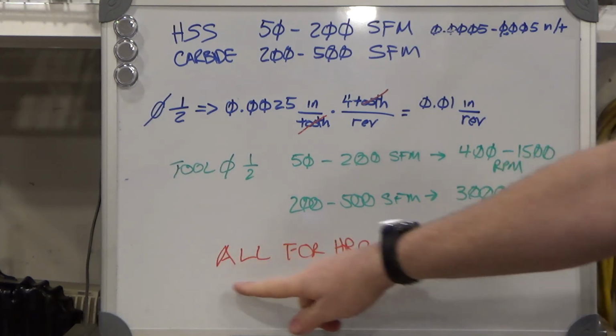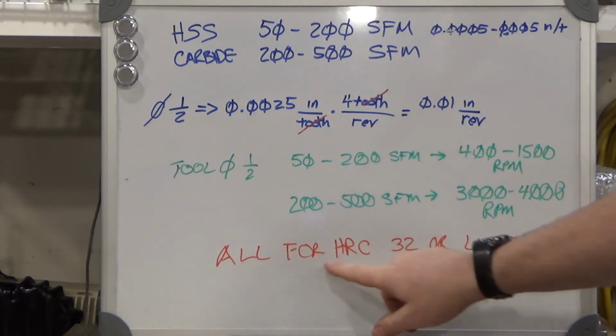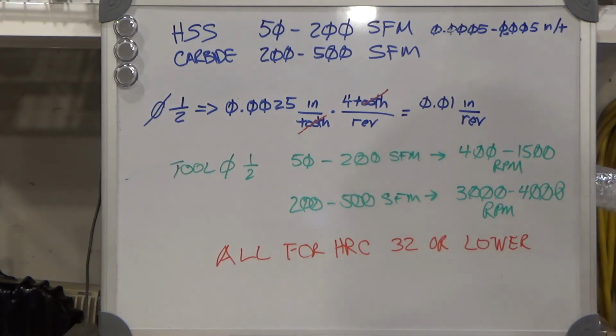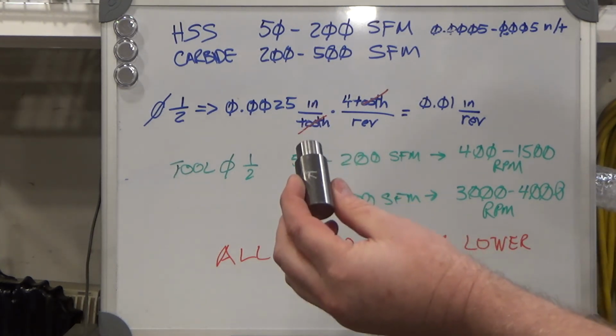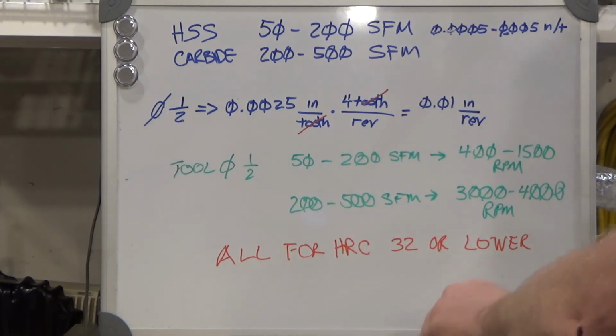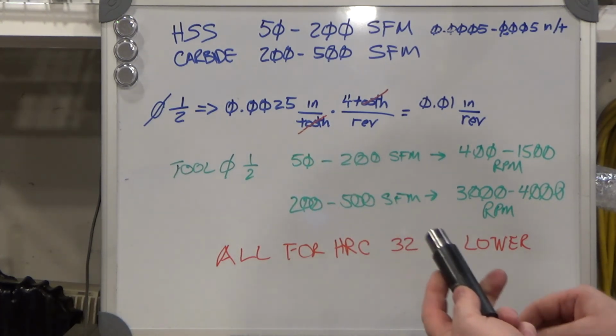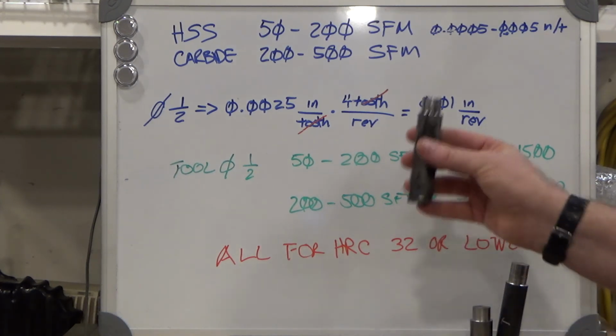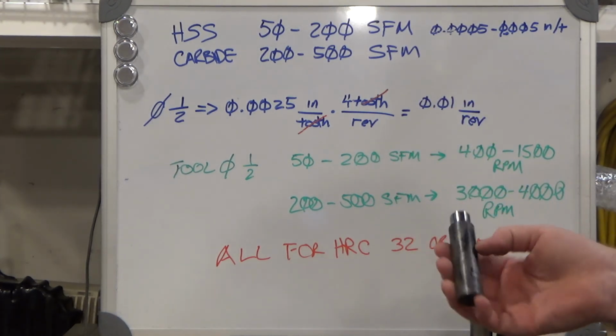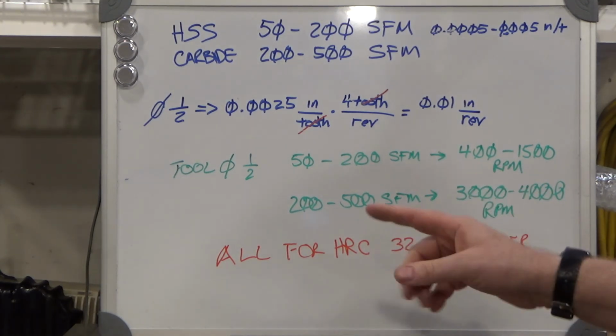However, they qualify all of these for HRC materials 32 and lower. So the annealed material is certainly below that. It's around 13. The hardened and tempered part is actually Rockwell 39 approximately. And the heat treated only part is Rockwell hardness 54 to 59. So as your hardness increases, your surface feet per minute need to go down accordingly. And if you don't, you will damage your cutters and have to buy new ones.